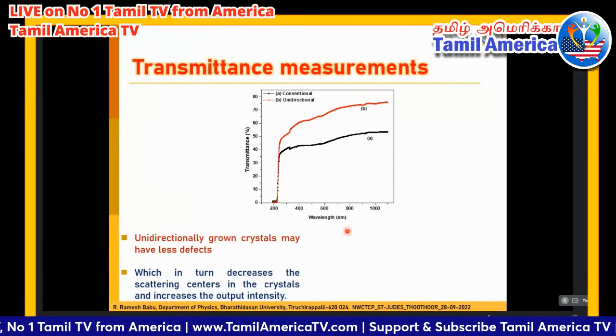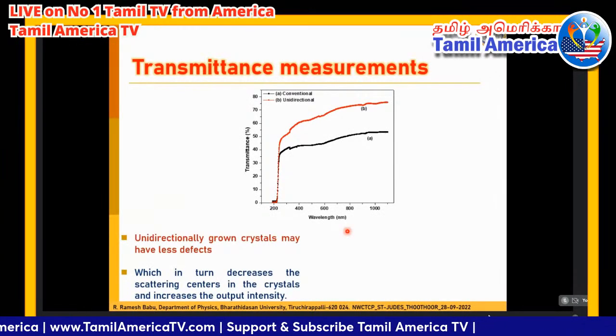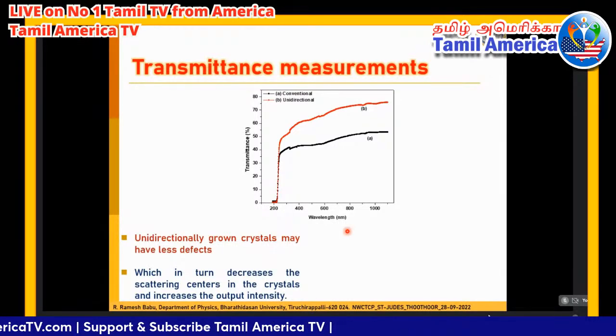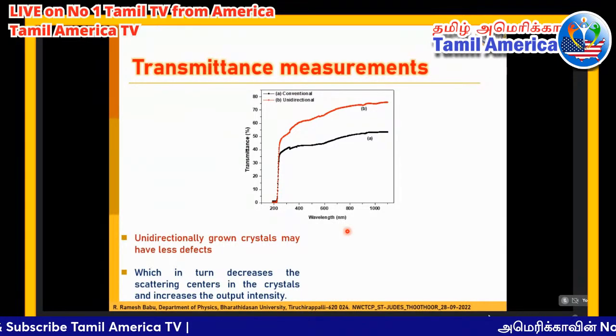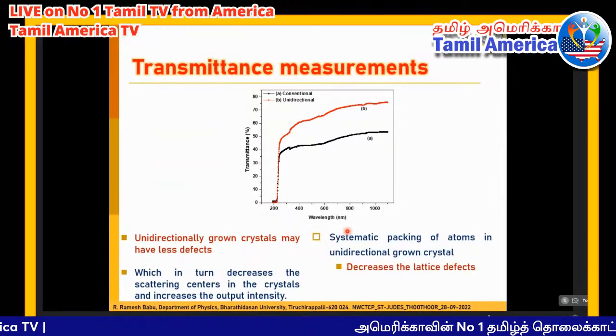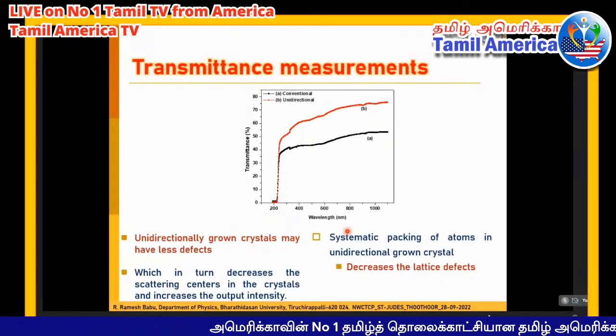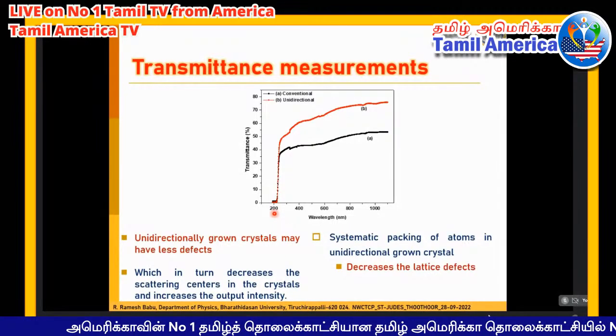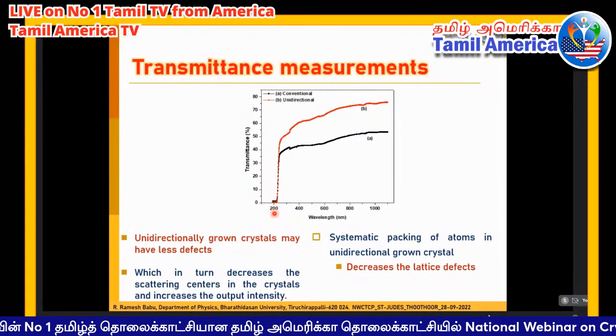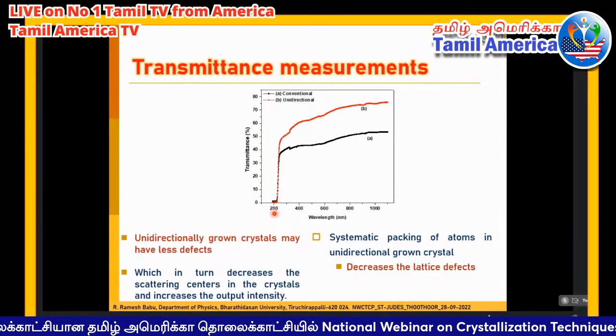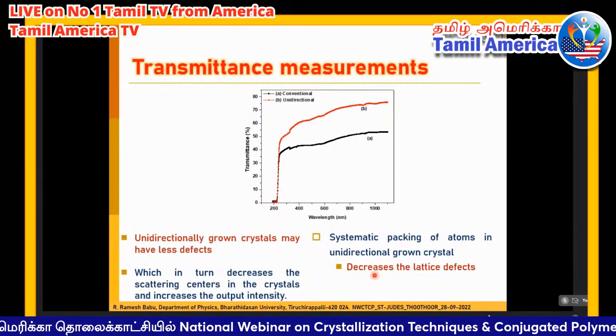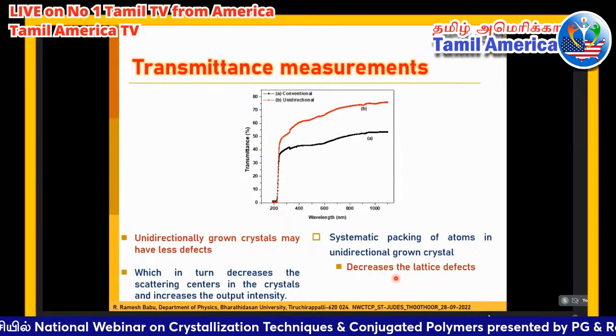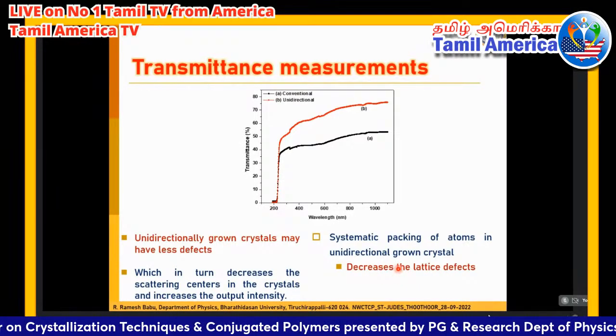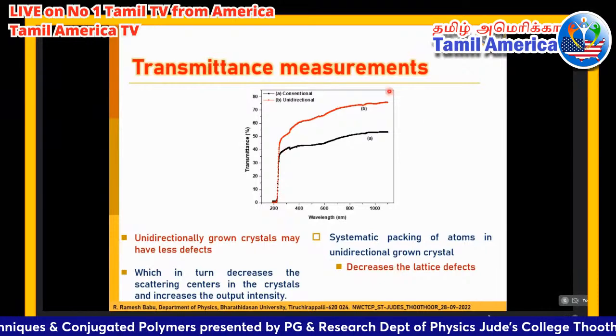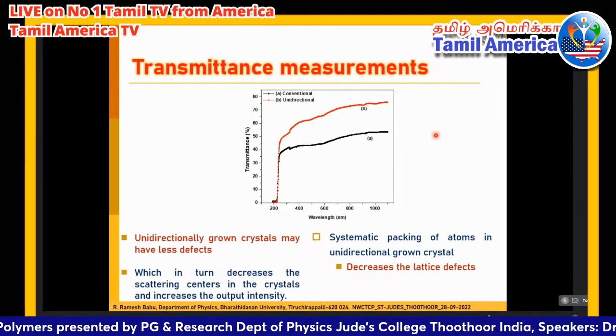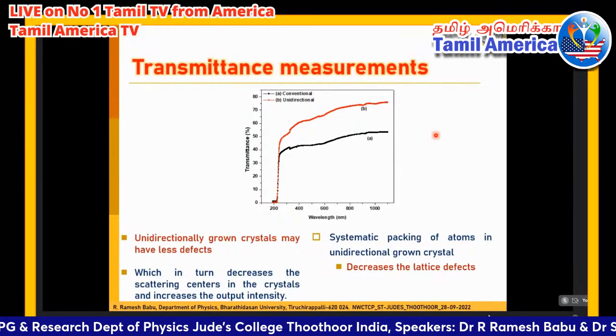We have also examined our grown single crystals and compared the data using the conventionally grown single crystals. The unidirectionally grown single crystals show high quality and high transmittance. In unidirectionally grown single crystals, the systematic packing of atoms exists, so that decreases the lattice defects. By decreasing the lattice defects, we can obtain high transmittance from these materials. We can minimize the defect centers, so that improves the transmittance of the material.